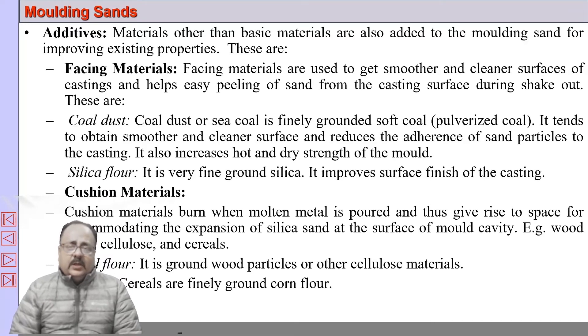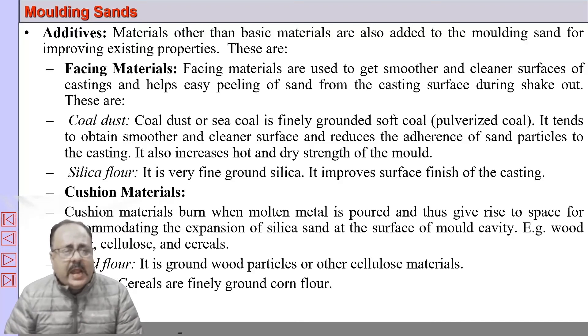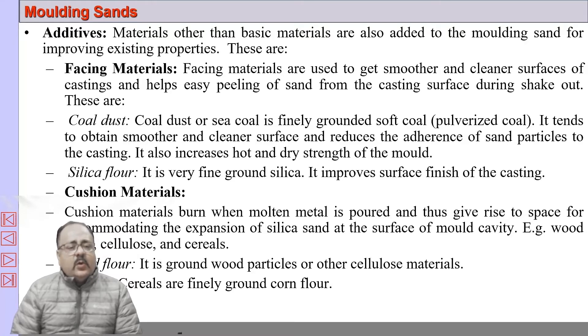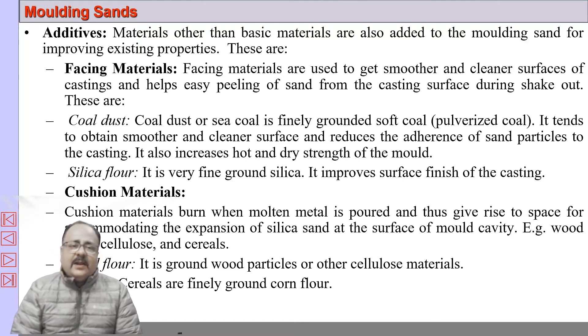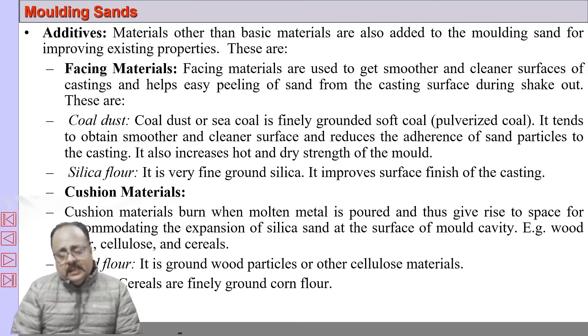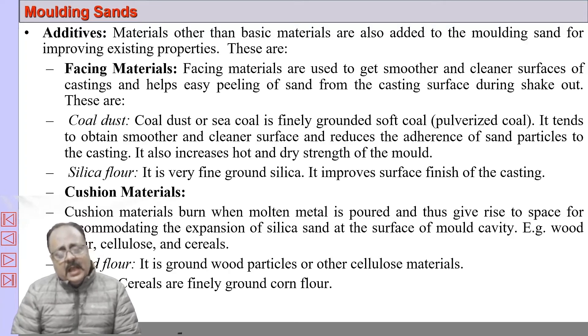Apart from silica grains, moisture, and clay, certain additives are also added to the molding sand. Some facing materials are added to make the sand smooth — coal dust and silica flour — which form the face of the mold. These are normally not mixed with the entire molding sand; rather, they are added to the facing sand only. The facing sand comes in contact with the molten metal, so its refractoriness must be high.